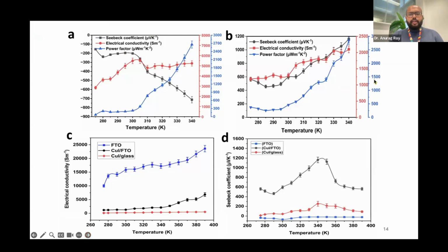A bit of a parameter when the device is formed: I have the device at this moment in my hand as a prototype. So this is a device, and you can see here there is an N type and there is a P type. The white one is the N type, the aluminum zinc oxide, and the yellow one here is the P type copper iodide. And we measure all the parameters, as I said, which are important to determine the figure of merit: Seebeck coefficient, electrical conductivity, and power factor. I will come to the thermal conductivity after that, but before that we need to understand these three factors, and those are pretty good results.